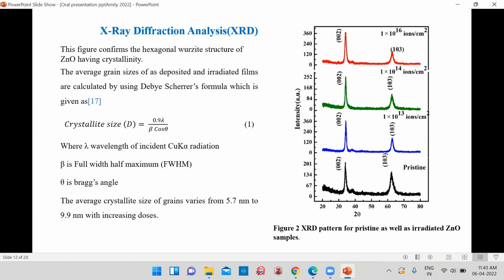We have calculated the crystallite size from the Scherrer formula given in the presentation, in which we get the crystallite size varying from 5.7 nanometer to 9.9 nanometer with increasing doses.